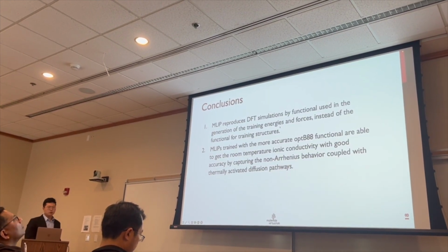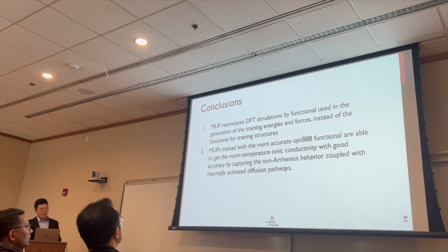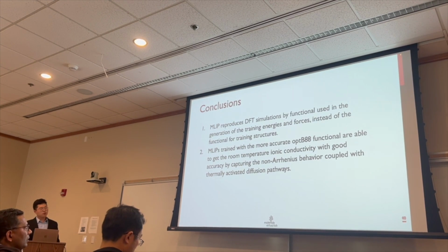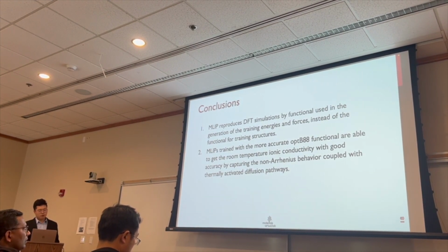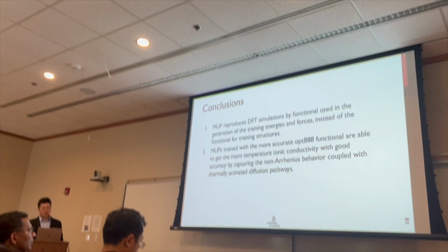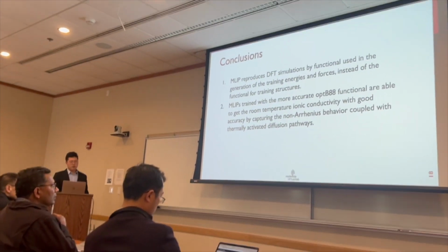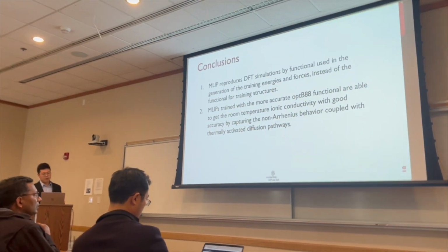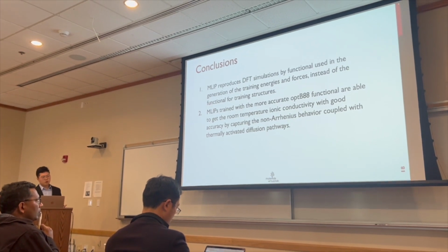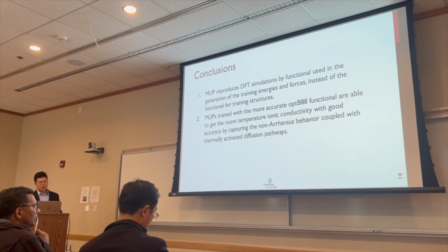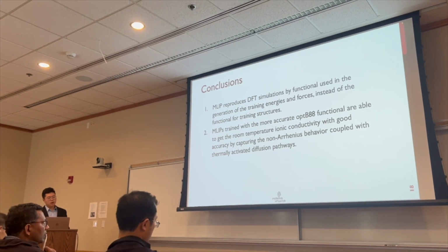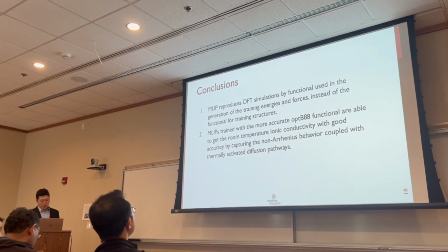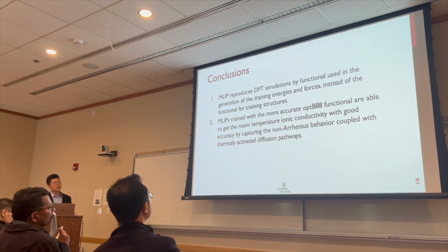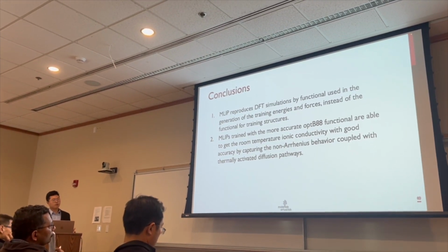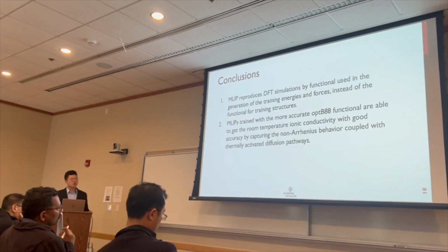So here I want to draw a quick conclusion for this study, where we show that MLIPs reproduce the DFT simulation by the functionals used in the generation of training energy and forces, instead of the functional used for training structures. Also, MLIPs trained with the more accurate functional, which is OPTB88 here, are able to get room temperature ionic conductivity with good accuracy by capturing the non-Arrhenius behavior coupled with the thermally activated diffusion pathways. Seeing this very good result, we are excited to apply this method to other systems that are practical for solid electrolytes, for example, the complex grain boundary structure.